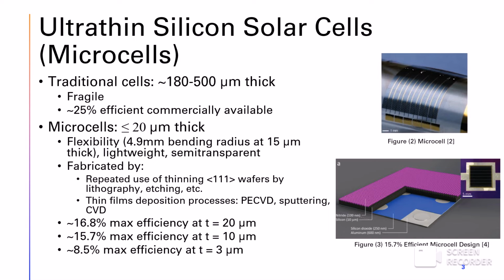A traditional silicon solar cell has a max efficiency of about 25%. Unfortunately, the efficiency of microcells is less due to using less silicon. So researchers have worked on techniques to improve efficiency by creating anti-reflection coatings and etching structures to trap light. A maximum efficiency of 16.8% has been reported for 20 micron thick cells and 8.5% for 3 micron thick cells.